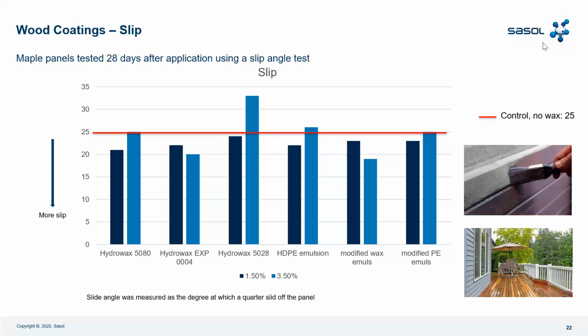The control, so without wax emulsion, achieved 25 in the maple test, and we have Hydrowax 5080 again that achieved very good performance of slippery, and then follow Hydrowax Experimental 004 and Hydrowax 5028 at 1.5%. And Hydrowax 5080 achieved the best result of all Sasol wax emulsions and also against the competition.